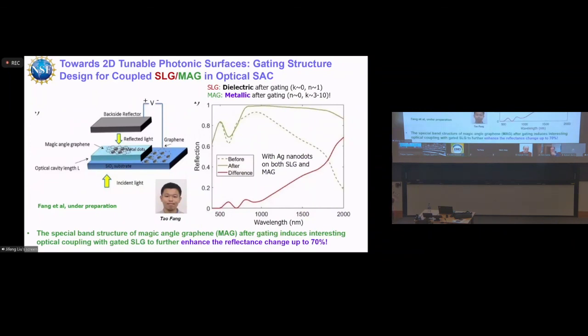coupling this magic angle graphene and graphene into this cavity. So without applying the electric field or gating, this layer is absorbing, this layer is absorbing, both enhanced by some nanoparticles that funnel light into them. So basically you get relatively low reflectance at the surface. But once you turn on the electric voltage, this front side graphene becomes transparent. The backside becomes a metal. That's why you get a very strong reflectance over here. You get a reflectance change of about 70%.